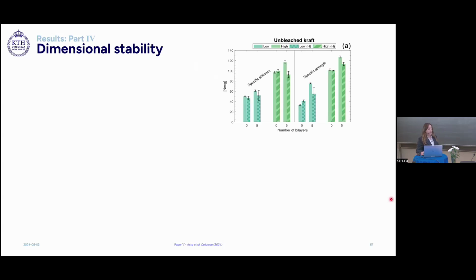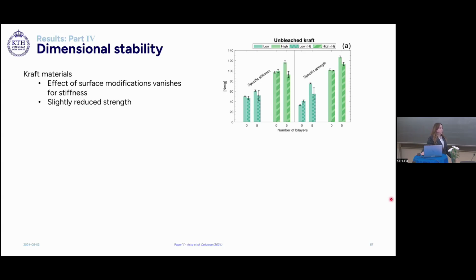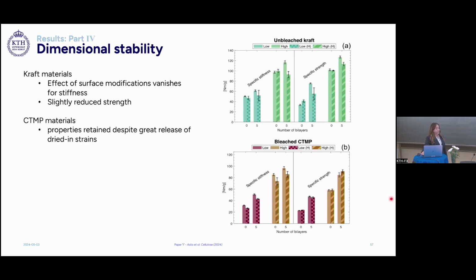The mechanical properties of the paper were also tested post the hygroexpansion, or post the moisture cycling, to assess how the moisture cycling affected the mechanical properties or the dried-in strains. And looking at the kraft material, we can see that the effect of the surface modification vanishes for stiffness, and there's slightly reduced strength after moisture cycling. And for the bleached CTMP materials, we can see that the properties are retained despite great release of the dried-in strains.